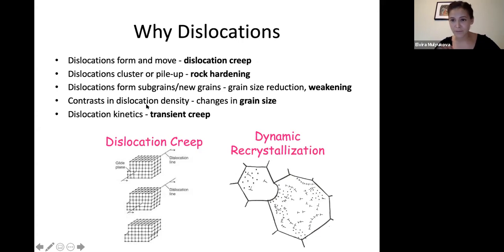Different grains may have different dislocation densities, and neighboring grains with different dislocation densities can induce thermodynamic forces onto a grain boundary, which would then drive the grain with a low dislocation density to replace the grain with a high dislocation density. This is just to say that the presence of dislocations puts a grain at a higher internal energy. This is analogous to normal grain growth, where smaller grains tend to be replaced by larger grains as they're at a higher internal energy state.